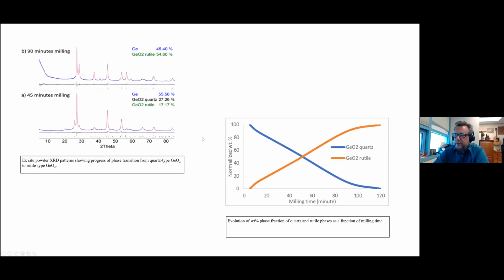You can monitor the phase fractions of the two phases. So we have quartz and rutile. You can see that quartz goes down with time, rutile goes up with time. This allows us to estimate the kinetic parameters of this phase change. You can see that we end up with powders that are milled to really small grain size. So powder diffraction analysis is really easy because you have pretty perfect grain statistics. The grains are fairly spherical and fairly small.